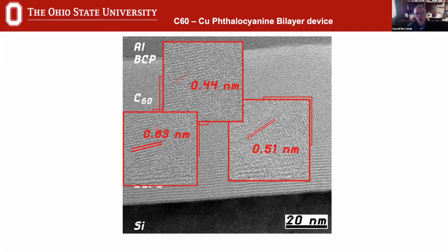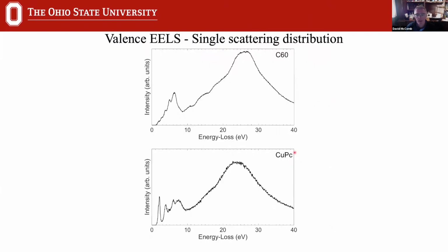And this is a cross section of an organic system. It's a bilayer system, so it's a layer of C60 and copper phthalocyanine. I'm just showing you this high resolution TEM image to show that you can make very, very high quality cross sections of these organic materials without actually causing damage. And you see all of the lattice fringes within the material. So these are really very high quality materials. Because we have a bilayer system, we can look at the two phases on their own. So here's a spectrum from C60, and this is the spectrum from copper phthalocyanine, which are our donor and acceptor phase in that simple bilayer.